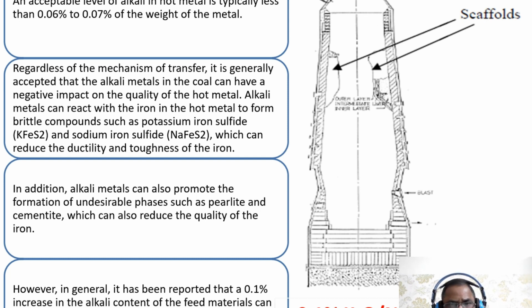Further compromising the quality of iron produced, it is essential to note that even a modest 0.1% increase in alkali content of feed material has been reported to correspond to a noteworthy 1% decrease in hot metal production. To put it into perspective, the impact is tangible. 0.1% alkali can result in an additional 6 kg per ton of hot metal coke consumption. This underlines the critical role of alkali management, not just in maintaining quality but also in ensuring optimal efficiency in the production processes. As we delve deeper, we'll explore the nuances of mitigating these challenges in the pursuit of high quality hot metal.